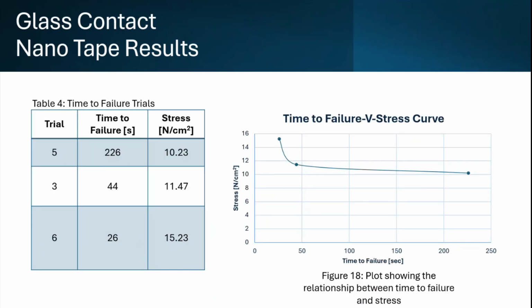All right, and here we can see the time to failure trials. I wanted to plot this because it showed something quite interesting. Theoretically, if you found the maximum stress, then the time to failure would reach or approach infinity. So we can see that the stress versus time to failure plot, that at around 9 or 10 newtons per centimeter squared, the graph starts to level out or reach an asymptote. So theoretically, if we had stresses even closer to the maximum, then this would reach all the way out into infinity. This is evidence to the fact that the maximum stress is somewhere between 9 and 10 newtons per centimeter squared.